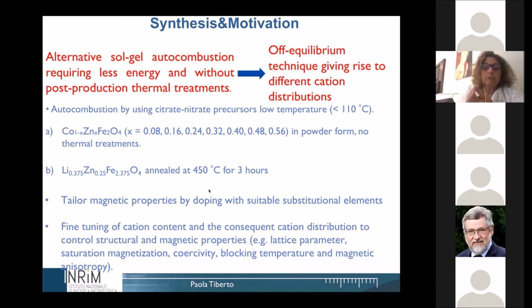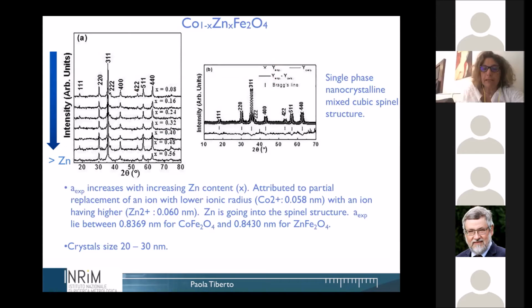Okay, the main parameters that influence the magnetic properties are obviously the microstructure, which leads to changes in saturation magnetization and in all the magnetic properties interesting for application. These XRD patterns simply show you that all our compositions are spinel. The lattice parameter increases with increasing zinc content because zinc has a larger radius, and all samples are nanocrystalline.